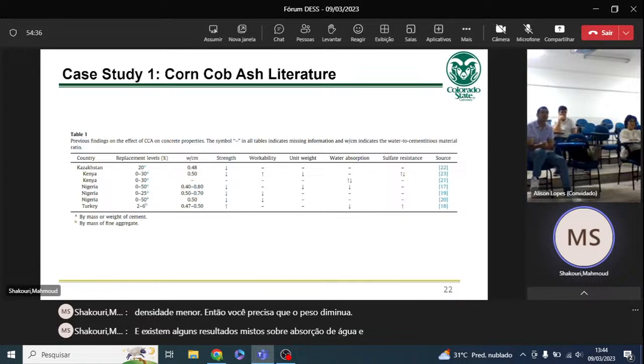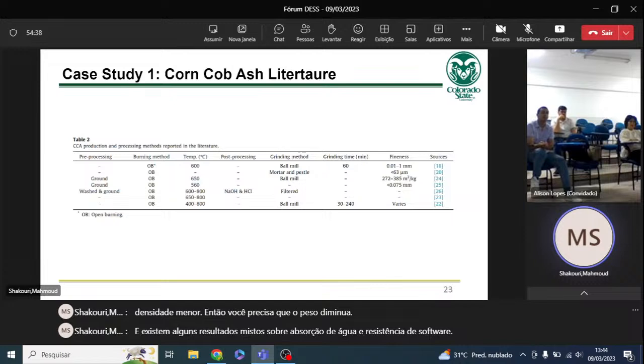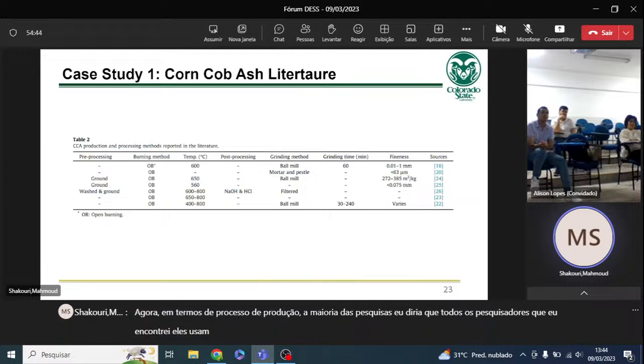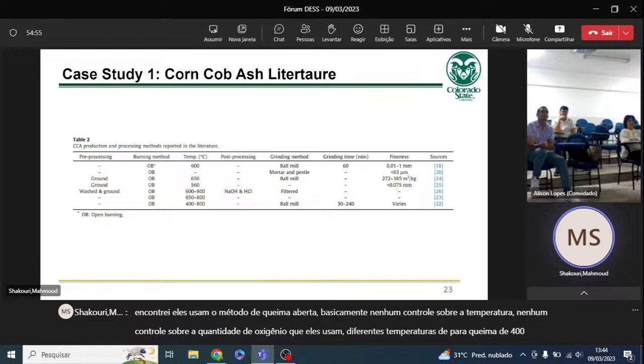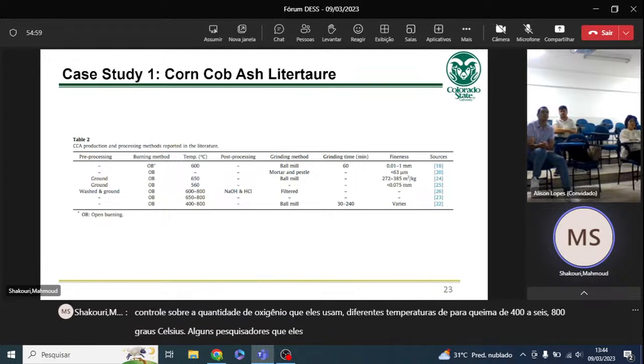Now, in terms of production process, most research, I would say all of the researches that I found, they use open burning method, basically no control over the temperature, no control over the amount of oxygen. They use different temperatures for burning from 400 to 800 Celsius. Some researchers did post-processing. The grinding method plays a very important role in the final properties of our ash.